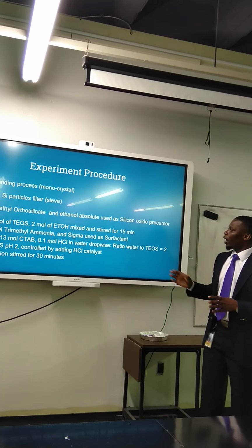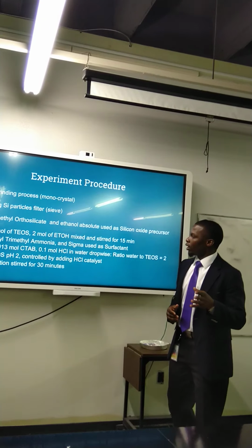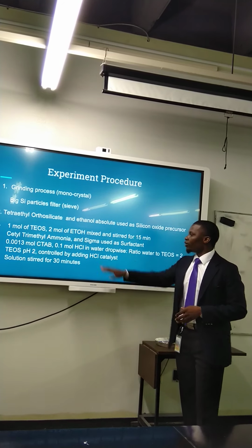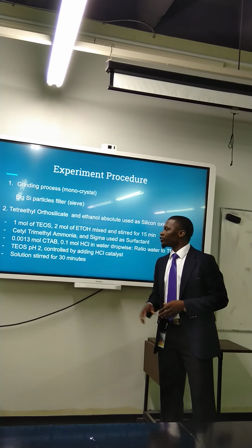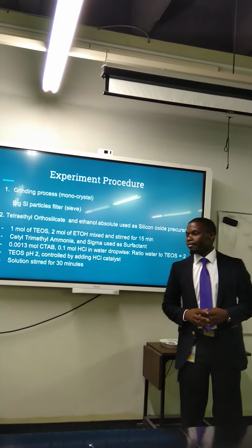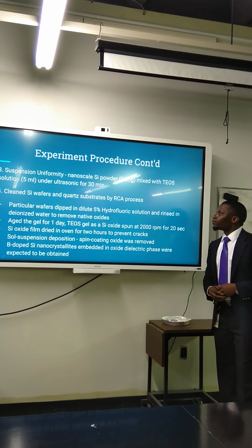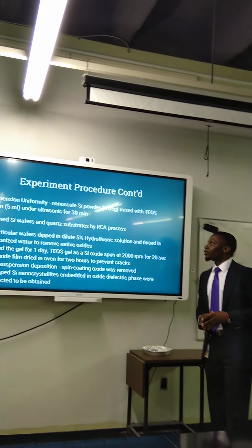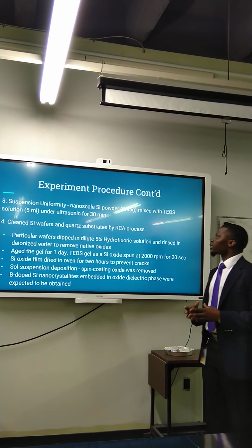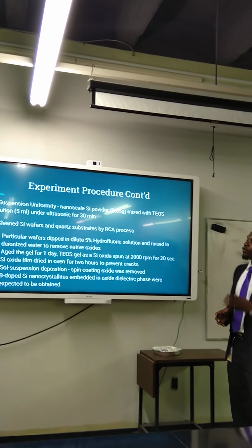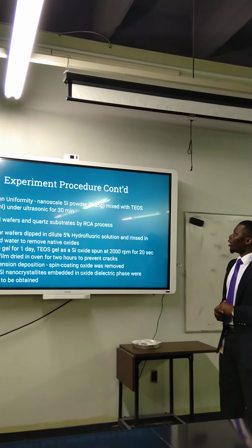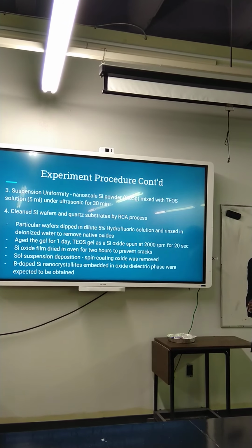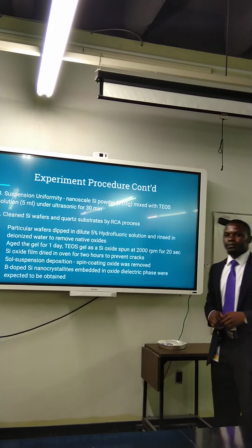After that, I made the CTAB solution, which was a combination of hydrochloric acid and cetyltrimethylammonium bromide. Again, to get suspension uniformity, 0.5 grams of nanoscale silicon powder was mixed with 5 milliliters of TEOS solution under ultrasonic for 30 minutes.